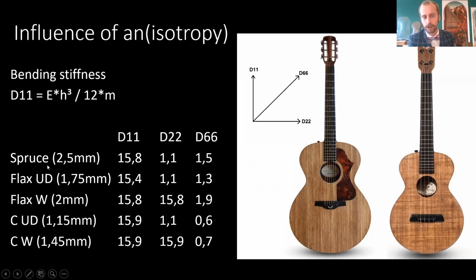When we change to a different material, flax fibers, for example, and we put it all in the unidirectional way, so the fibers are similar like this guitar, we actually end up with a different thickness, but we can make the stiffness in the different directions comparable to each other. If we use woven flax, however, we end up with a stiffness which is a lot higher in one direction. So you see that if we change these fibers and the fiber orientation, we will change the behavior of the plate. So interesting to take into account.